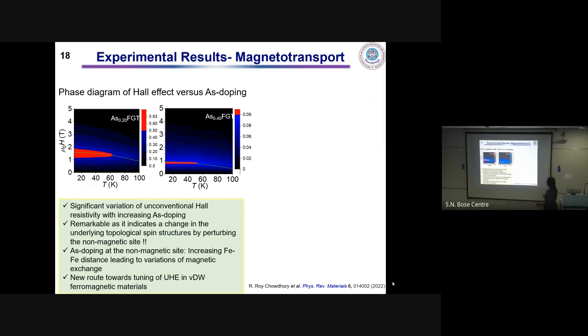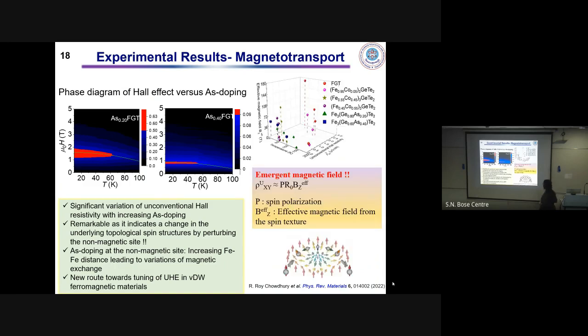So we have also tried to estimate the effective magnetic field that the conduction electrons can feel if they traverse through this kind of Skyrmion-like textures in the system, and it basically feels a fictitious magnetic field which gives rise to the topological Hall effect. So we have tried to estimate that, and the effective magnetic field that we have observed is maximum for FGT, and it gradually decreases as we increase the non-magnetic site doping with arsenic, and the same behavior has been observed for the non-magnetic site doping also.